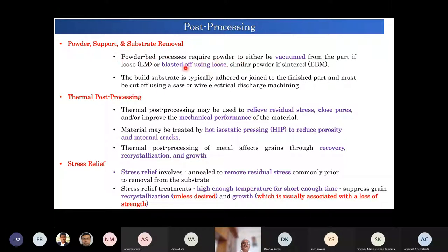So these are to be removed. Powder bed processes require powder to be either subjected to vacuum from the part, or blasted off if the process is sintering based, like in EBM processes. And then there is a thermal post-processing that is required to relieve residual stresses, close porosity, and optimize the microstructure. Then porosity optimization is done by hot isostatic pressing.